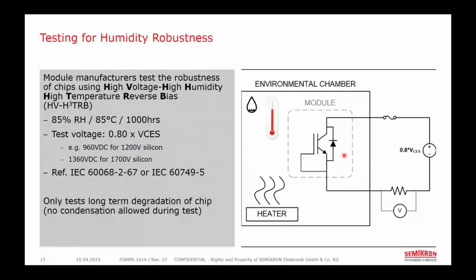As a side note, in the past, this test was performed with only 80 volts and was known simply as an H3TRB test. Later on, it was determined that the impact of the voltage on this effect is very high, and the test voltage was increased to that 80%, and the new name of high voltage, or HV, H3TRB, was used.